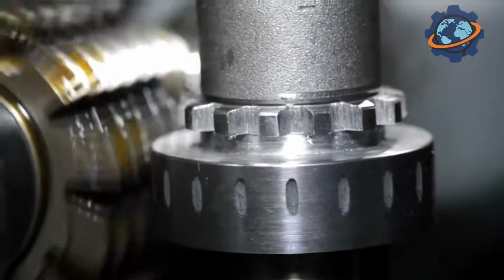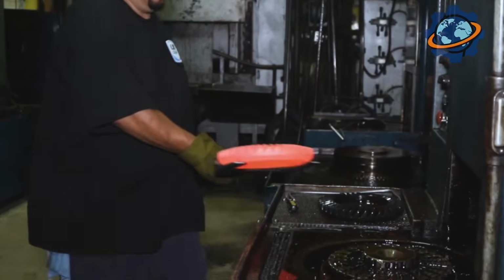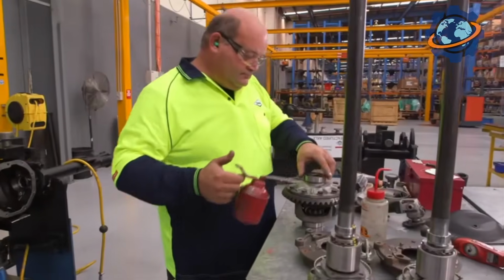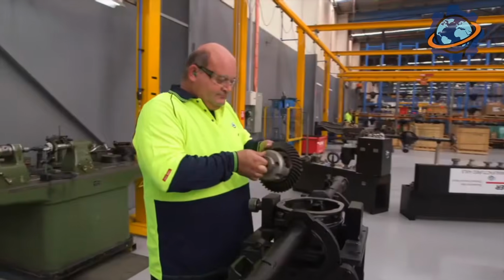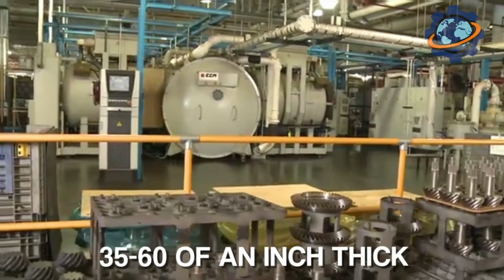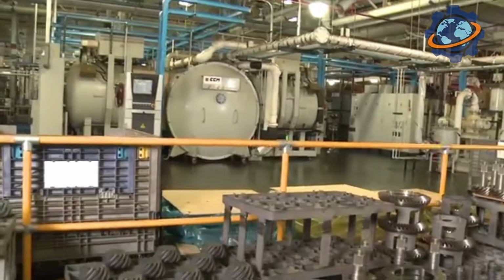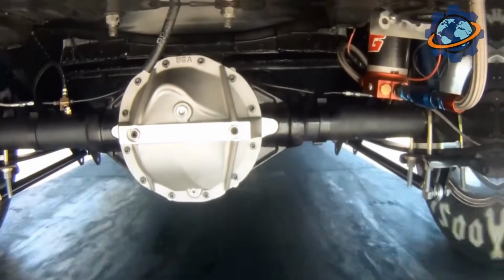After cutting comes heat treatment, carburizing in a carbon-rich gas atmosphere at 1700 degrees Fahrenheit for 4 to 8 hours. The tooth gains a hard, wear-resistant surface layer 35 to 60 thousandths of an inch thick, while keeping a tough core that absorbs impact loads without cracking.